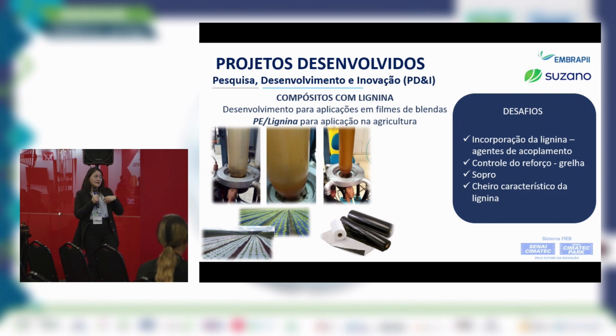The incorporation of lignin, because this requires the coupling agents, the aggregators, the control of the filler. Since we use the blowing system, we really need to control the lump formation. Lignin lump formation, because then the film cannot expand properly, and we need to be careful with the use of grates in the input. It's difficult to work with a blowing system because if there is any contamination or if there is any lump, this will hinder the process, especially in the blowing process.